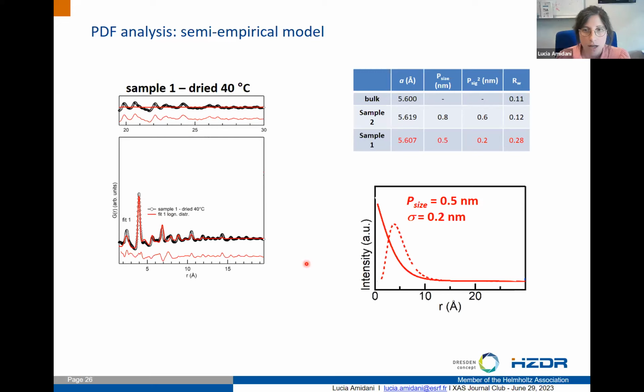We initially used an approach that is done in PDF to estimate nanoparticle size. We just damp the signal with a function that takes into account the nanoparticle as a distribution of sizes. This is what I was getting if I try to simulate the signal with this distribution of sizes. It's not a super bad fit.